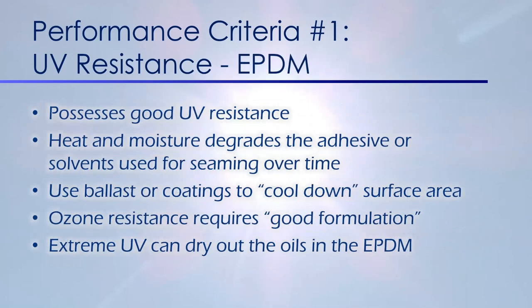When we look at our thermoplastics and thermosets, we look at the UV resistance of EPDM. In its earlier stages, UV resistance is good with EPDM. However, we know that this is a thermoset product. It is vulcanized in the manufacturing process, so we can't heat weld the seams. And we have to rely on adhesives and tape to keep the seams closed and protect that roof. Well, over time,